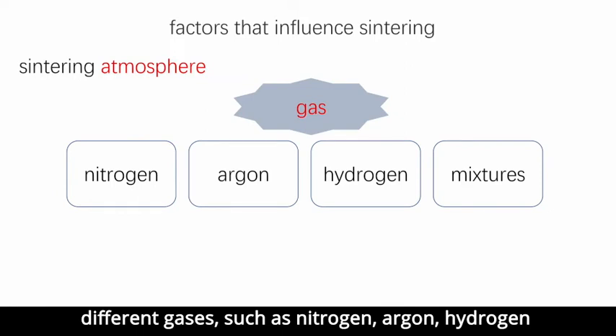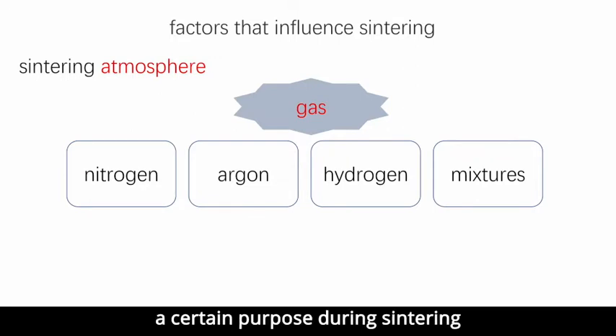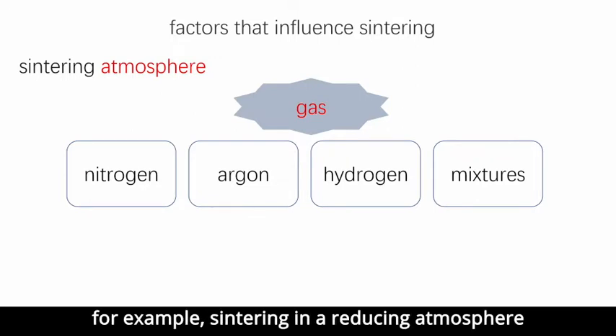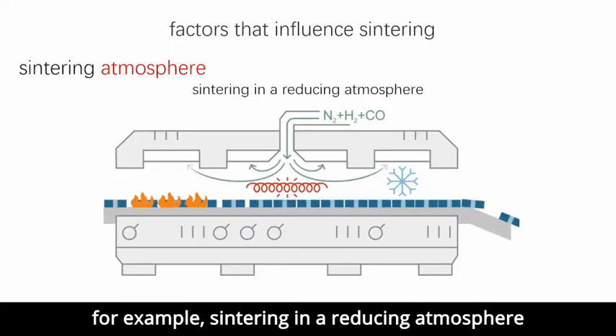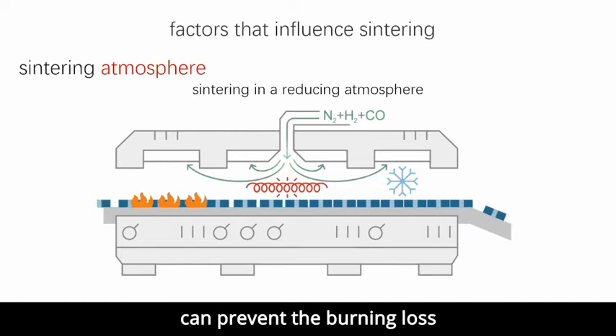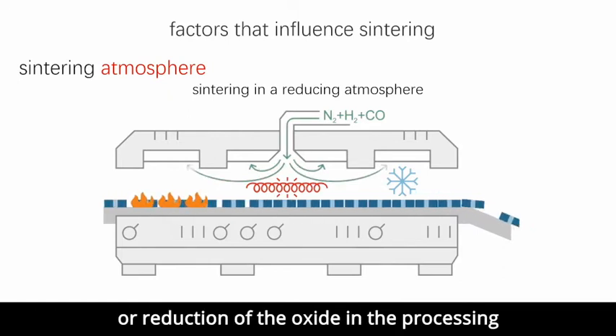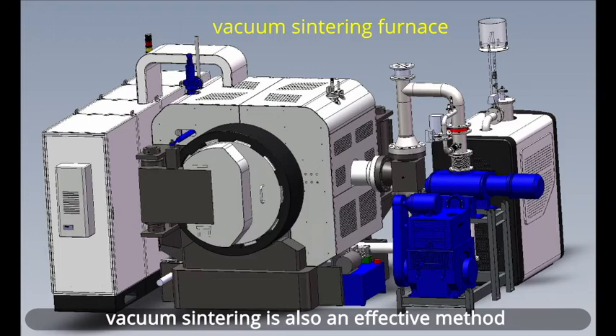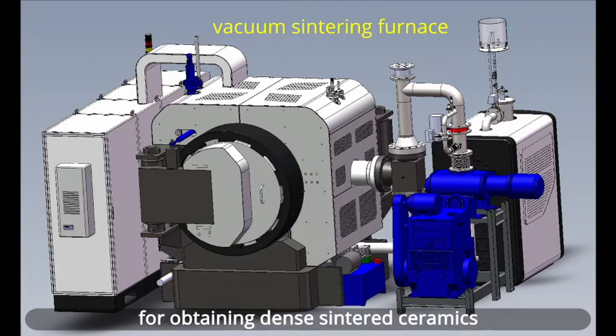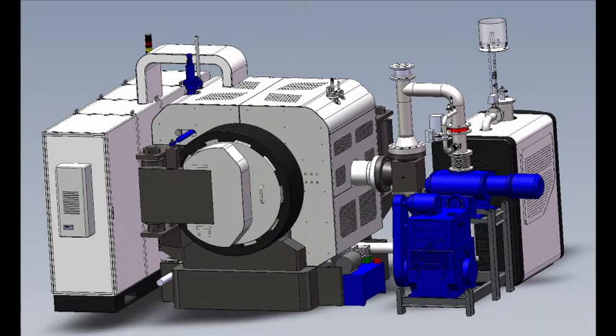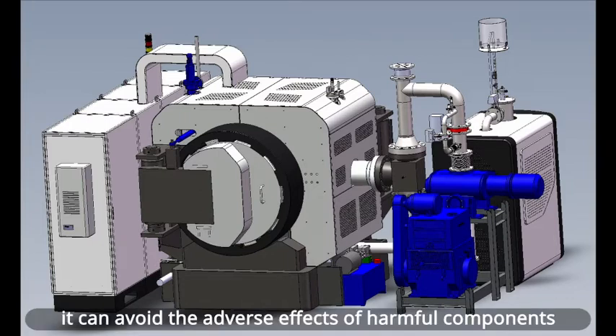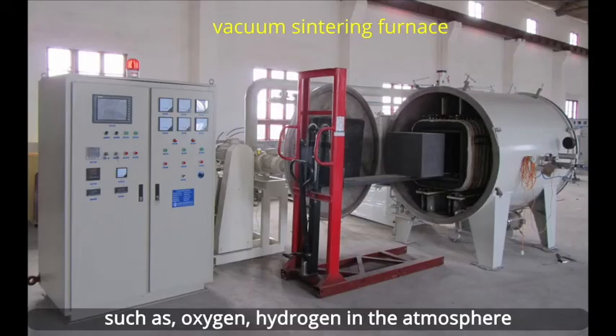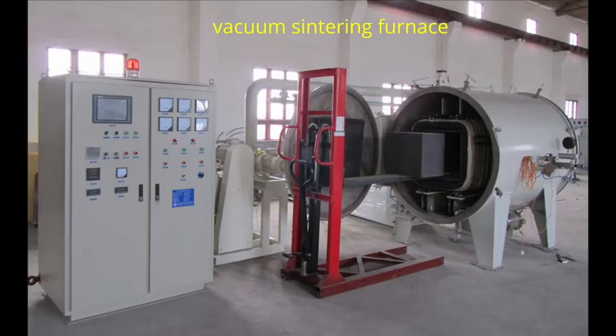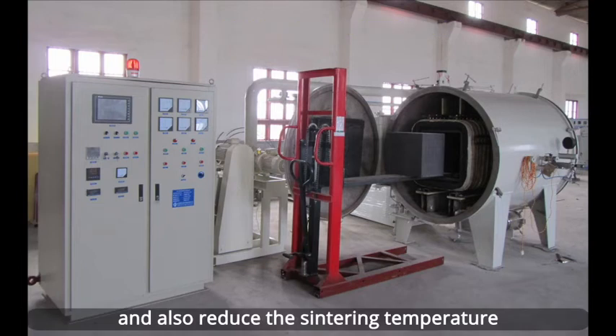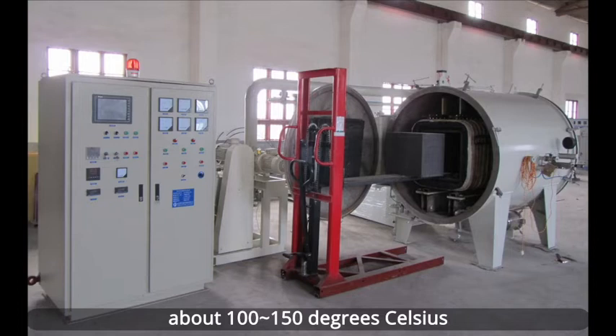Different gases such as nitrogen, argon, hydrogen, or their mixture can be used for a certain purpose during sintering. For example, sintering in a reducing atmosphere can prevent the burning loss or reduction of the oxide in the processing. Vacuum sintering is also an effective method for obtaining densely sintered ceramics. It can avoid the adverse effects of harmful components such as oxygen and hydrogen in the atmosphere, and also reduce the sintering temperature by about 100 to 150 degrees Celsius.